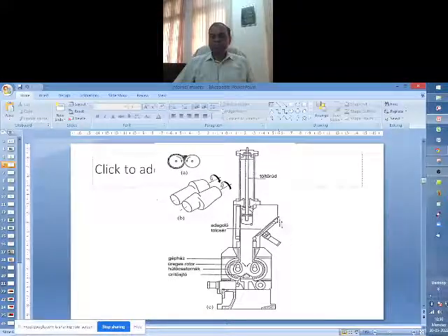That is done by automating the system. This will be opened up and there will be a conveyor system here with a balance attached. All the ingredients are placed on the conveyor belt, weighed to their respective amounts. As the conveyor belt rotates in one direction, all the ingredients will fall here, and it will jerk in between so that everything falls in. For the oil, there can be a mechanism to inject it directly, so you don't have to add it. Because the conveyor belt can put them all together in a continuous running mode, the feeding is in the shortest possible time. Once it is fed in, the sequence is programmed in the system so that the operation is totally automated.